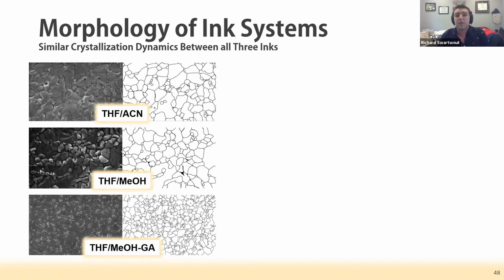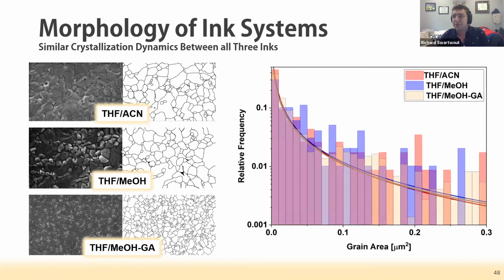We plot this out by the relative frequency of those domain sizes and fit it to a traditional log normal distribution, which is very commonly done with grain size analysis. The actual size distribution doesn't matter here. What matters is that all 3 of these inks have the same distribution, meaning that within these inks of interest, they're forming relatively the same film, which is great from an engineering standpoint because it means this Hansen model is useful for creating a wide variety of ink systems.